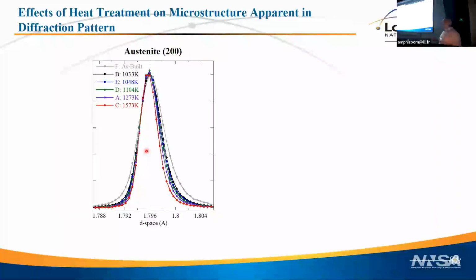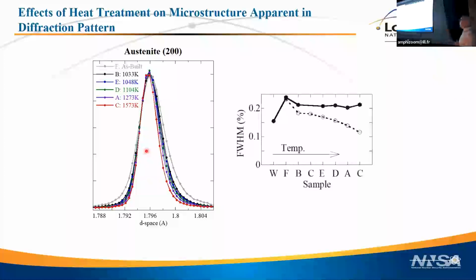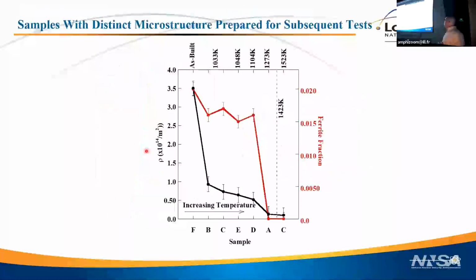Well, again, if you want more details, let's talk later, but I'm going to argue that that's just dislocation density. I told you in the beginning of the talk, don't believe anything about peak width. Now I'm going to ask you to believe me. You can see here's just a plot of how that full width at half max changes with sample, but in actuality temperature. So we can pull out things like, here's the dislocation density as a function of increasing temperature. That drops off relatively quickly, sooner than we would have expected. Here at about 750 C, the dislocation density has already dropped significantly. It continues to drop with further temperature increase.